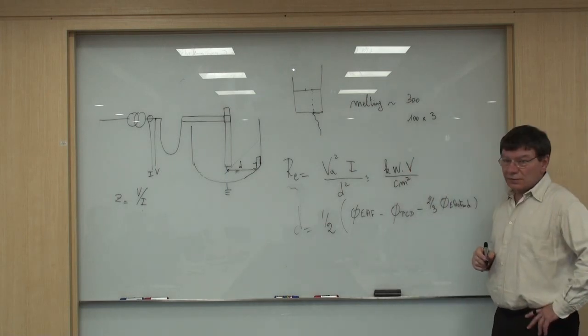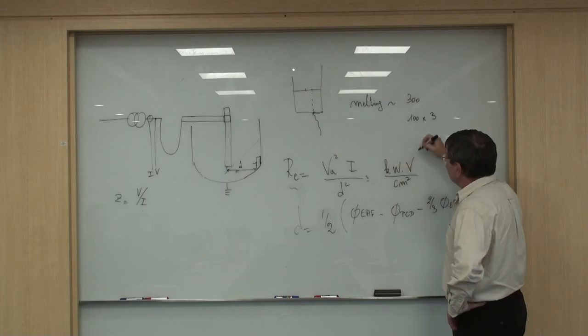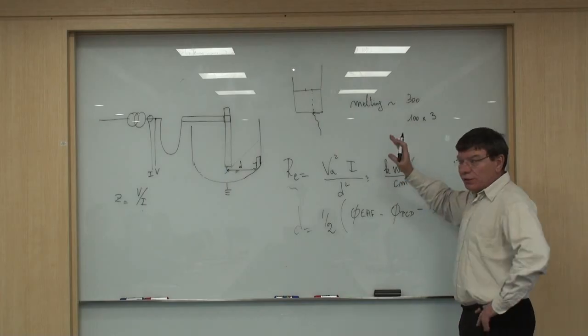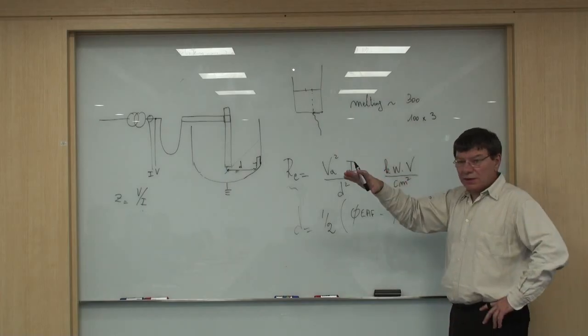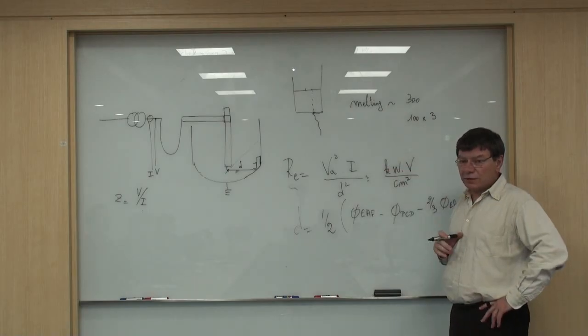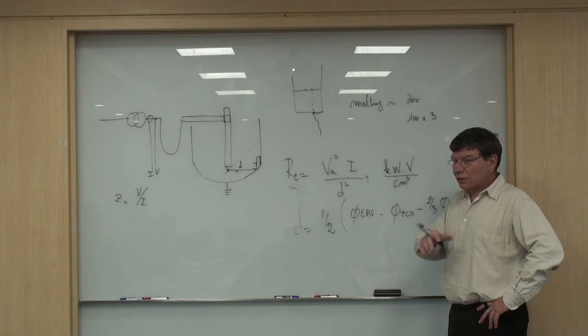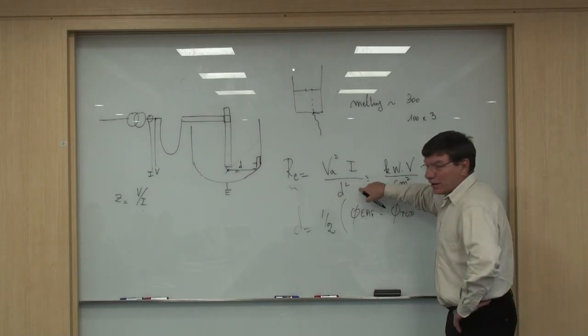With foaming slag, we can go to 300 as well. It was limited to 100 in the past without foaming slag. You mean the heat flux from the surface? Radiation from the arc.